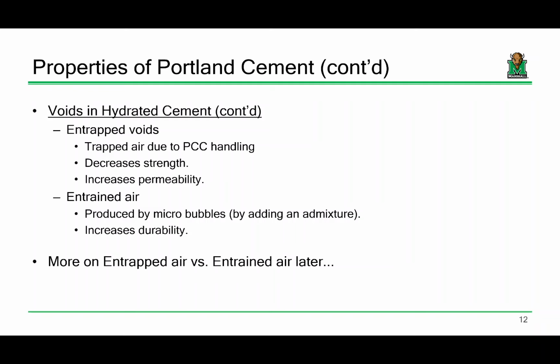Entrapped voids, that's not good, okay? Entrapped voids are whoopsies. Those are what happen when the concrete was handled poorly, it was placed poorly, it decreases strength, it increases permeability, which is really bad for external applications. What do we put on the top of the road in February in the great state of West Virginia? Salt. And we don't like that stuff to permeate into the concrete because if that hits the rebar, it rusts, metal rusts, it expands.